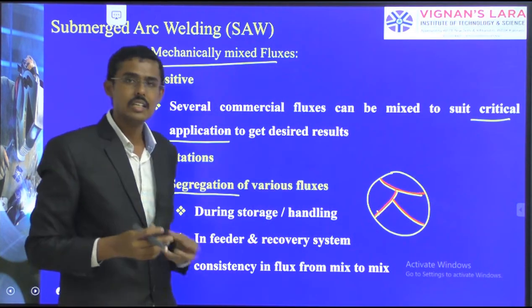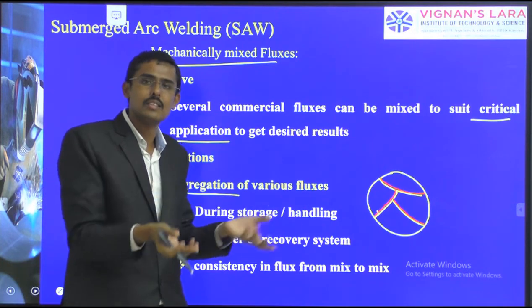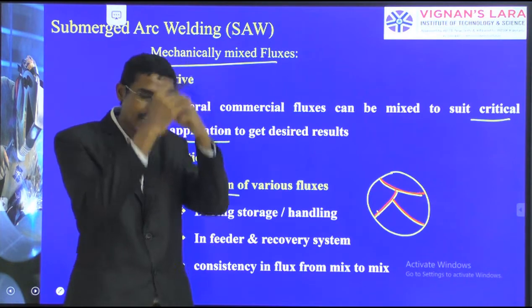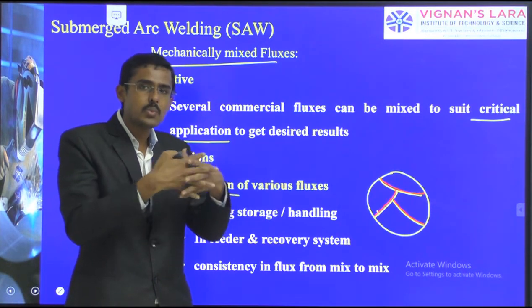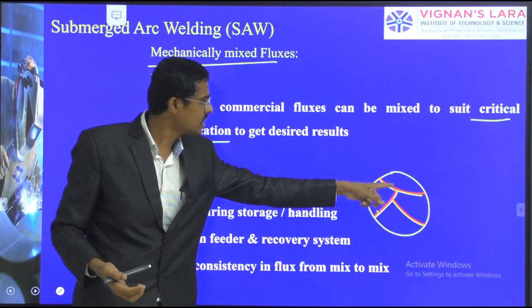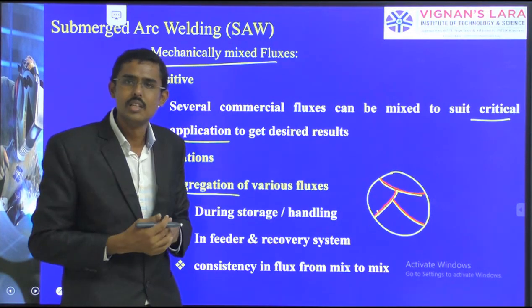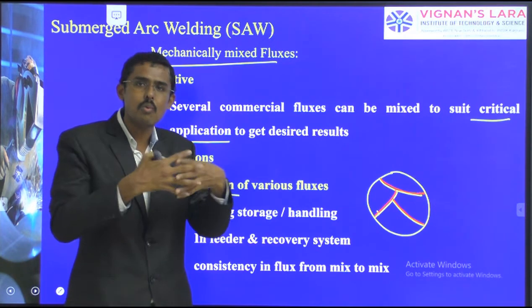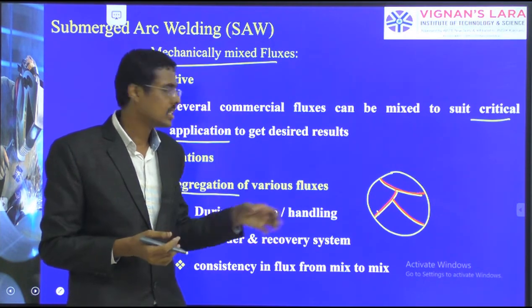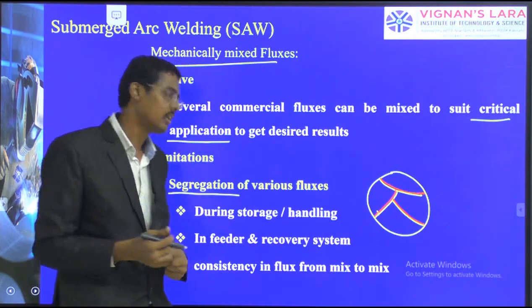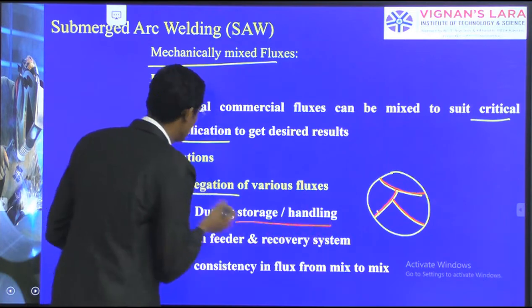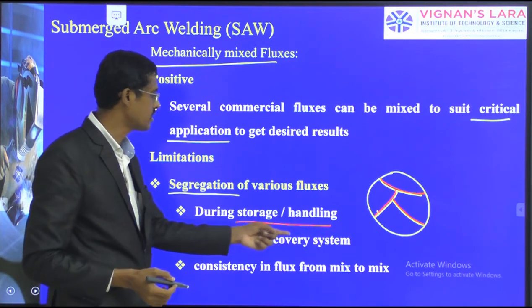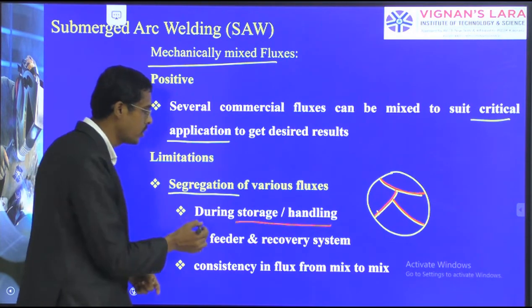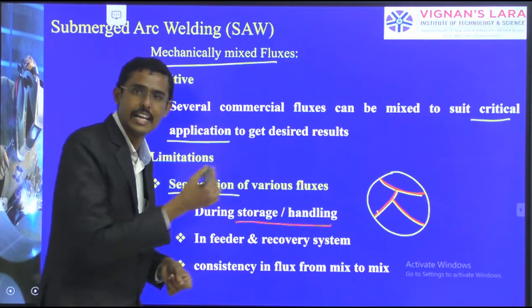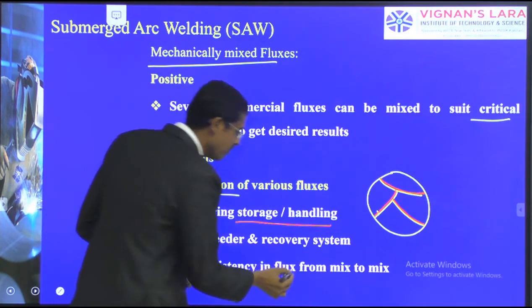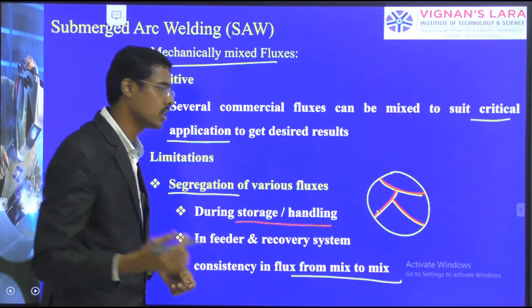So the segregation decreases the property, and fine grains will not form. If it is segregated in the boundaries, how will the next layer form? Next grains will attach with the previous one and strong bonding will not be there. Therefore, this decreases the property of the material. So during storage or handling, this will occur. And also in feeder recovery systems, segregation happens. The segregation may happen during storage, during feeding with respect to attachment to the environment, and also consistency in the flux formation of one-by-one mixing properties.